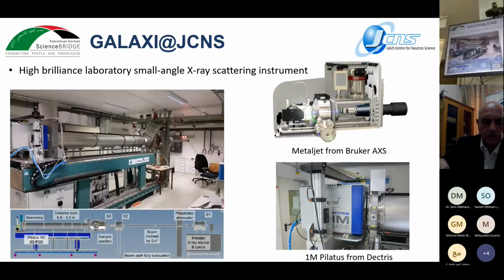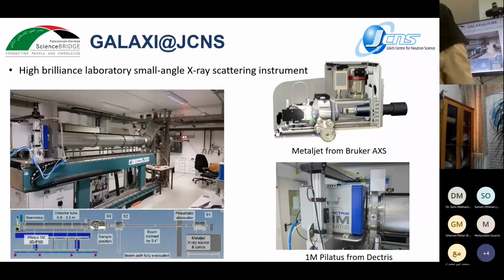So as I said, the measurements were performed under small angle or grazing incidence at the GALAXI instrument at JCNS, which is a high brilliance laboratory small angle X-ray scattering instrument, and currently I'm working as a local contact for this instrument together with Emmanuel Kentzinger. Here you can see a picture of this instrument, which is located in three separate rooms. In the first room, behind this wall, is the X-ray source. We have a metal jet from Excillum.